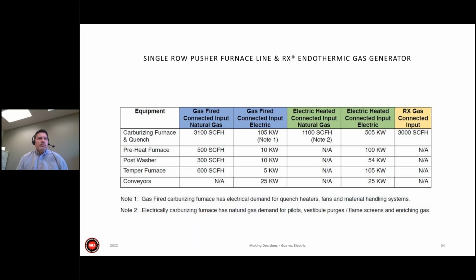This is a table showing in blue the gas-fired versus electric options for a single row pusher using process endothermic gas, RX gas. Process gas has its own carbon footprint, but it is required in order to do the value add process for heat treatment. So that will be carried for either option here, gas or electric. In the carburizing furnace, it says 3100 connected, but really it's 2000 for the heating. In the electric heated, you can see there's 1100 CFH of natural gas required, and the notes down below say that is for intermittent flame screens and for purges, and then the column for enriching process gas is always required. So this just gives a sum total and a comparison that we can calculate and offer both types, even for continuous pushers.